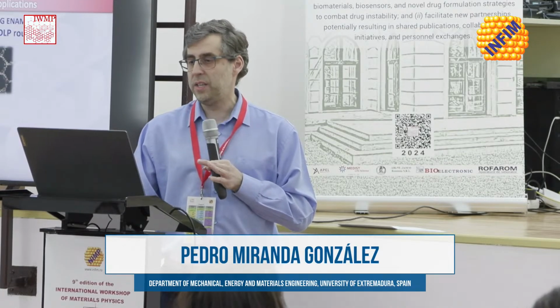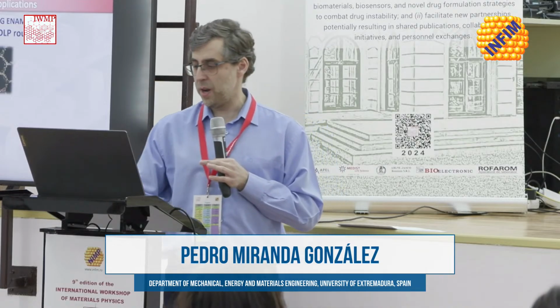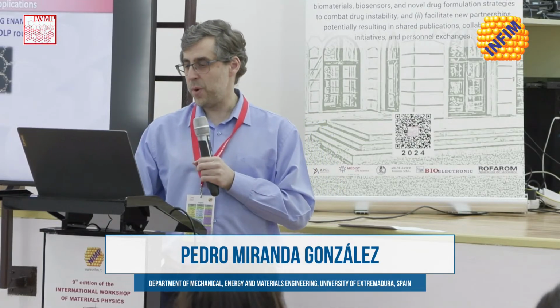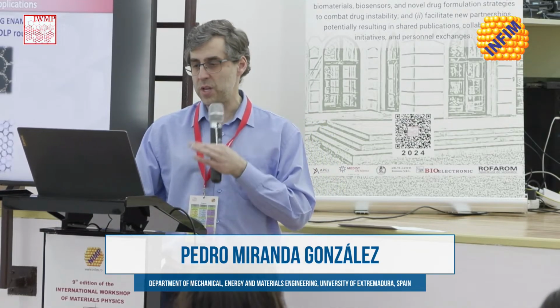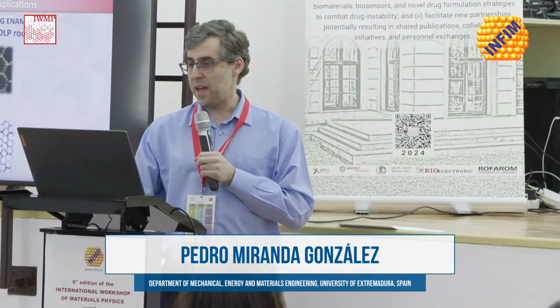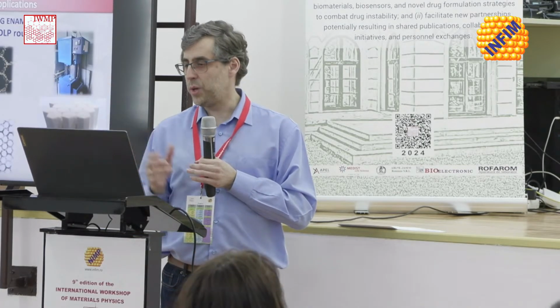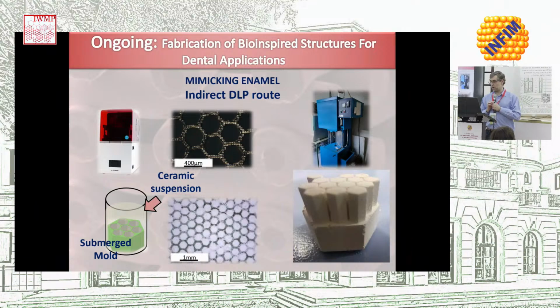By the indirect DLP route, we produce a polymer template. We submerge the mold in the ceramic suspension, we fill it up with ceramic, and then we heat treat the whole structure, and we get the rods. Unfortunately, this is proving very cumbersome and difficult because the debinding and the burning up of the initial resin mold is producing cracks.